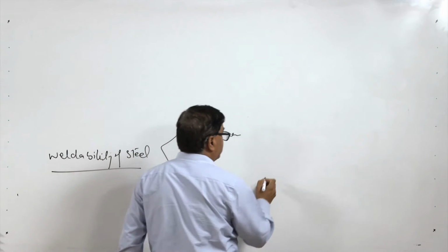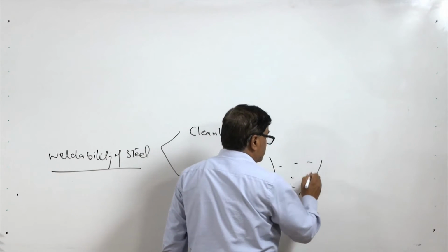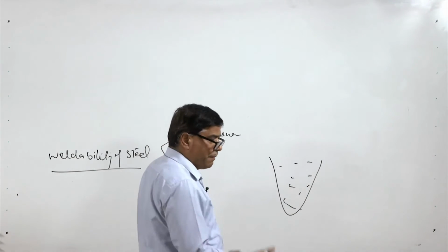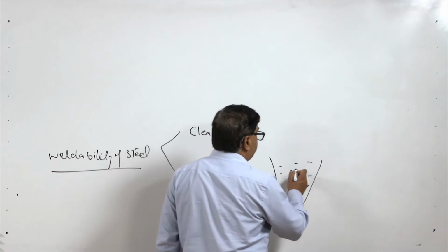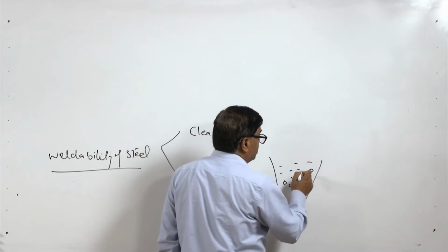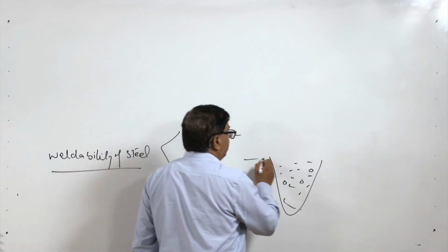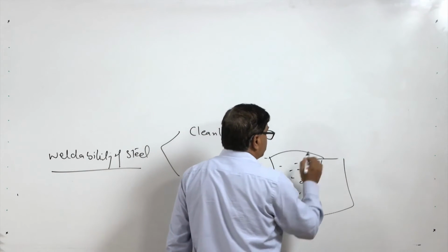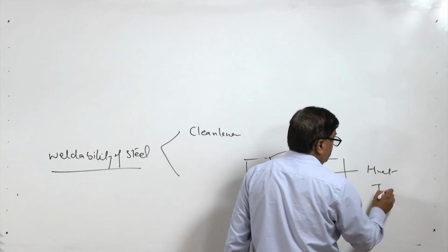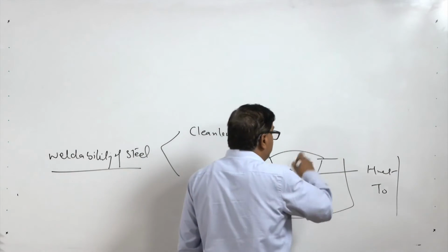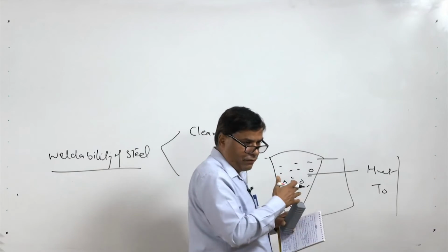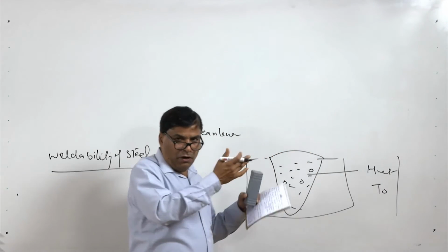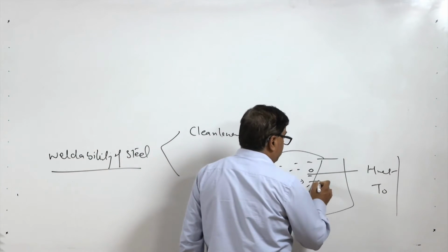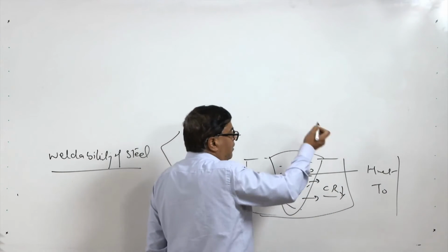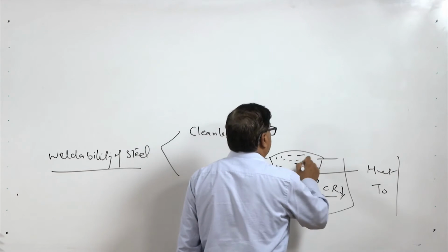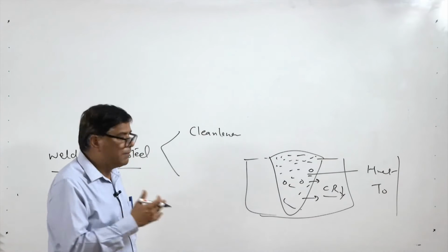As far as the solidification aspect is concerned, if the weld metal is solidifying slowly, then all the gases will be expelled, and the tendency for entrapment of inclusions and gases in the weld metal will be limited. But if the solidification is fast, then gases and inclusions have a greater tendency to get entrapped, and thereby the cleanliness of the weld metal will be reduced. The solidification is governed by H net and T naught, apart from the thermal properties of the material. Greater the heat input, longer the time for transfer of heat, so solidification time will be long and solidification rate low, because the cooling rate experienced is less. This allows sufficient time for inclusions and gases to come out of the weld metal, and thereby cleanliness will improve.